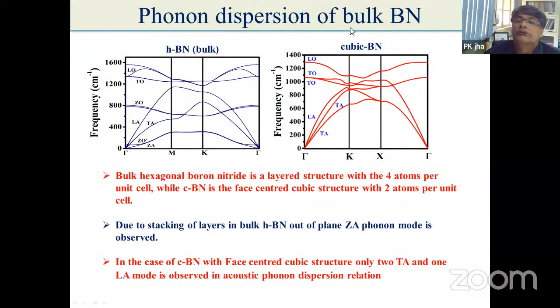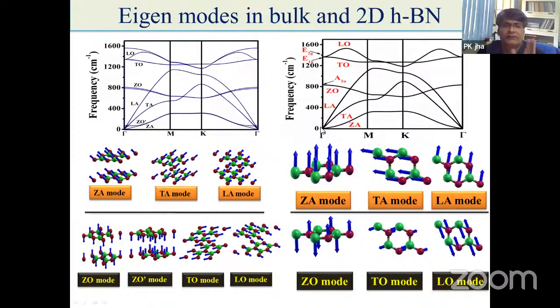Now here comes the phonon dispersion curve for the bulk BN. These are the two structures for the hexagonal and the cubic boron nitride. So you can see here the bulk hexagonal boron nitride is a layered structure, as I have shown you, with 4 atoms per unit cell. While cubic boron nitride is the face-centered cubic structure with only 2 atoms per unit cell, and that is why the phonon dispersion curves are different. Due to the stacking of layers in bulk hexagonal, the out of plane ZA mode is obtained. In the case of cubic boron nitride with face-centered cubic structure, only 2 TA, transverse acoustic, and 1 LA mode is observed. So this is what is the difference, right?